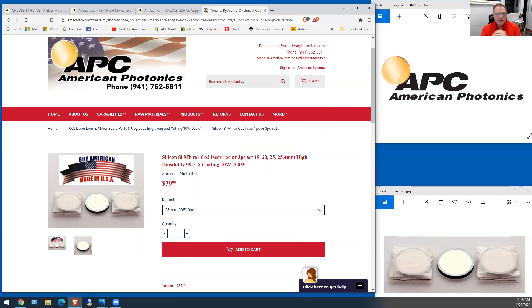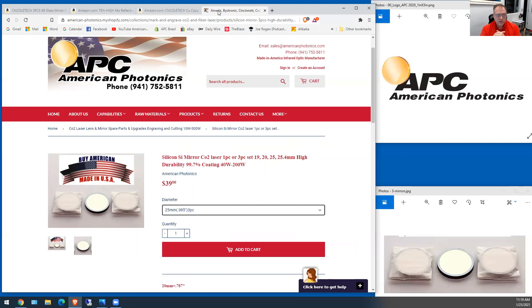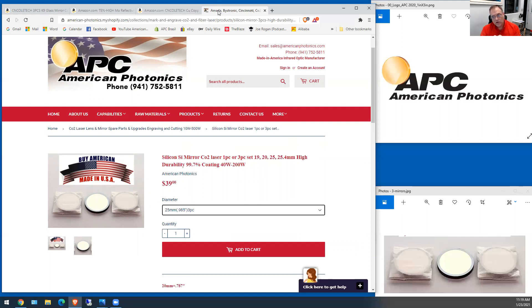And it's actually harder. It's a military crystal used for thermal imaging cameras which is more durable than zinc selenide. And it is actually a little bit more difficult to evaporate because you could get it about 300 degrees a little bit hotter to get it evaporated. But it actually when it goes on it's harder and if you look at my mirror it's silver.